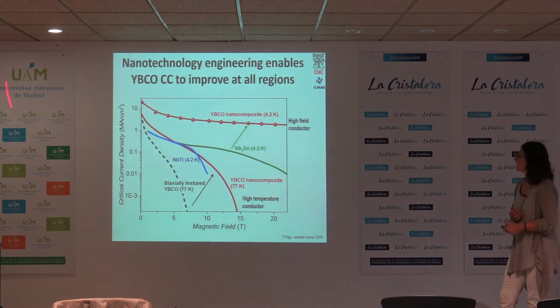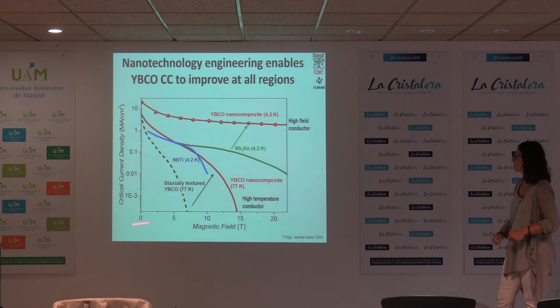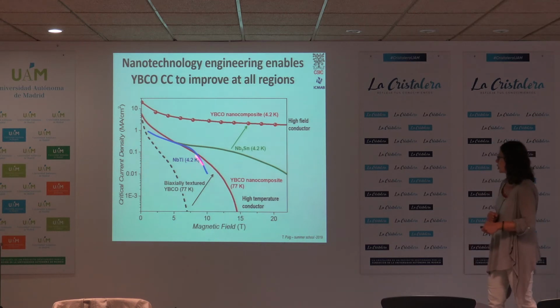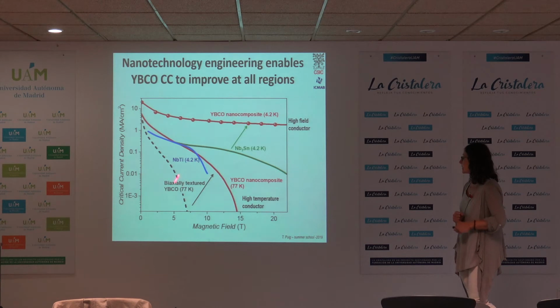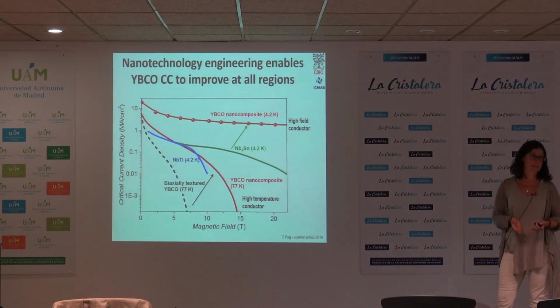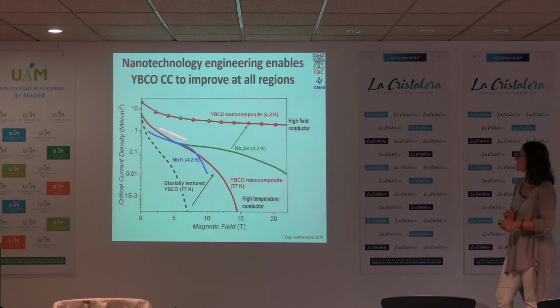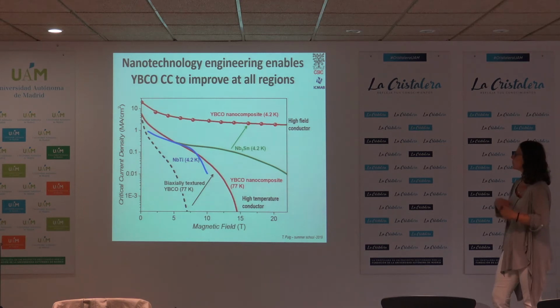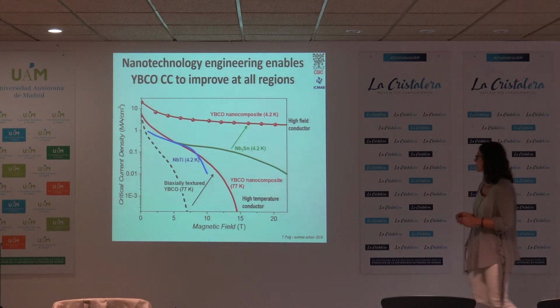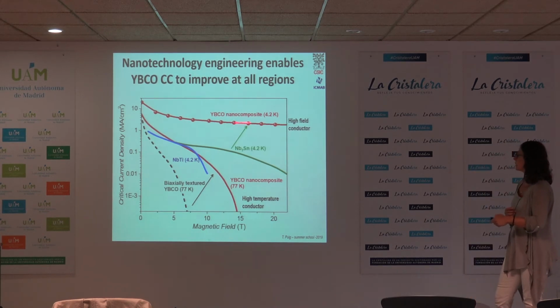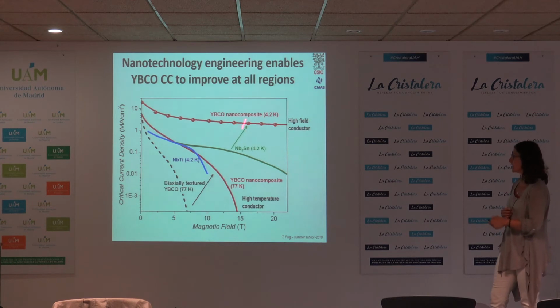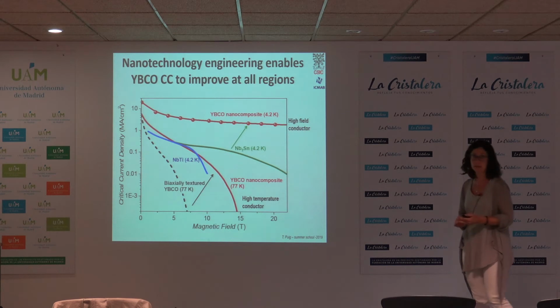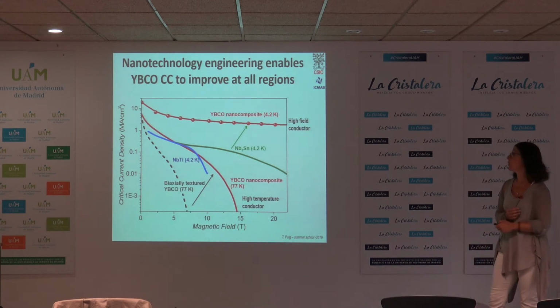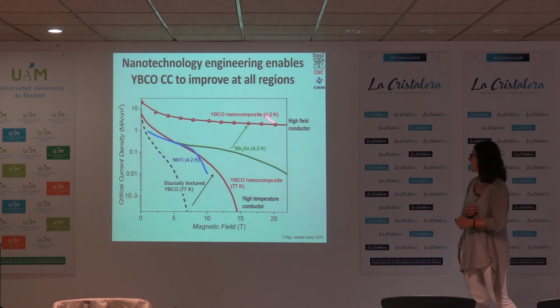At the end, what we see is that if we look at the critical current density as a function of the magnetic field, this is the niobium-3 tin at 4.2 Kelvin. This is the YBCO coated conductor at 77. But if we are able to properly put in pinning centers, we can go from this line to this line. And if we now go with this kind of defects to low temperatures, and we control the pinning landscape engineering, we see that at 4.2 Kelvin we are also able to get YBCO at these values, which are much higher than the low temperature superconductors. And that's why at this moment many of the applications are also thinking of YBCO at low temperatures as a high field conductor.